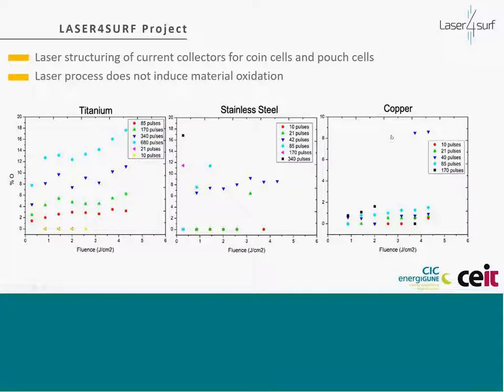So you can see here these graphs, the vertical axis is the oxygen content of the surface of the material after laser irradiation. Depending on the fluence, which is mainly related to the power of the laser, and the number of pulses, which is related to the scan speed or the process speed, we can have different oxygen contents for different conditions.